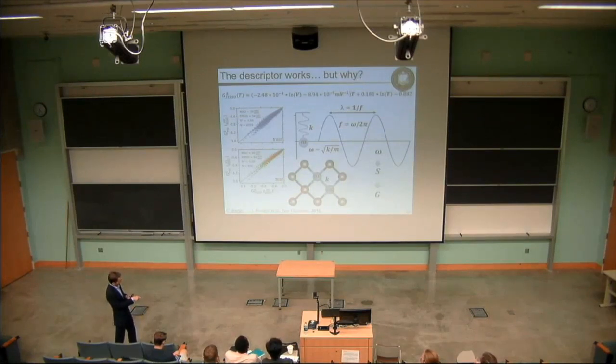And so ultimately, we can take the phonon frequencies of these vibrations, relate that to the entropy and ultimately to the Gibbs energy. The way these terms manifest themselves in the solid state is that we have some masses attached to each other by chemical bonds, and these chemical bonds have some stiffness. We presume that the atomic density in our descriptor is acting as a surrogate for the stiffness of those bonds, under the thinking that a material that's more dense has stiffer bonds, which is not too much of a reach.